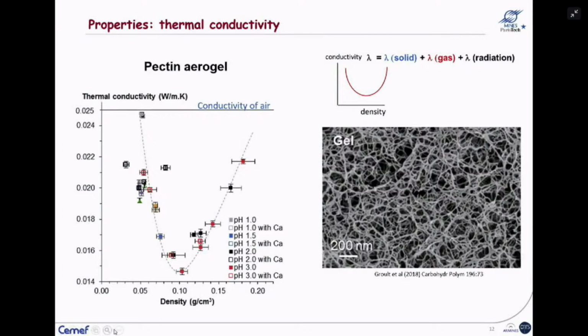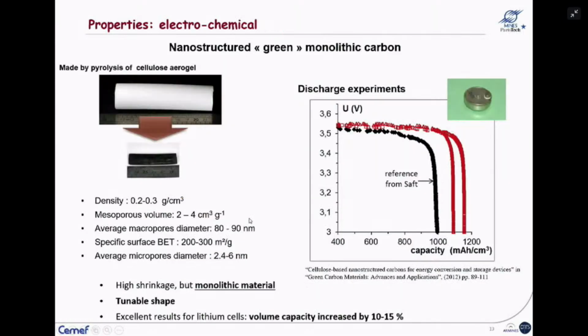And again, the most beautiful example is for pectin aerogels with very fine network. And you see the conductivity of the air is marked here, 0.025 watt per meter per Kelvin, and all data are below. And it is making a classical U-shaped curve of the conductivity as a function of density.